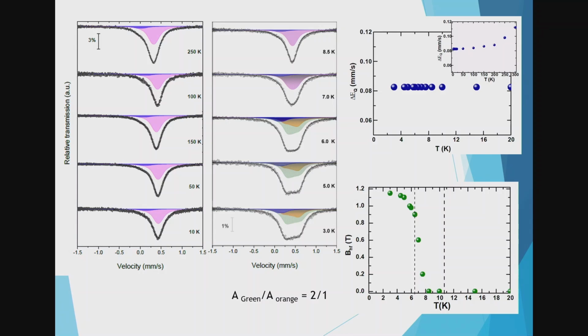And I assume these samples are polycrystalline samples. Polycrystalline samples, yes. Would it help to study single crystal samples? Yes, it would help a lot if I could find somebody to make it for me with iron 57. Yes, and I have a little bit of iron 57. This is a very nice sample to grow because of congruent melting, and it's very easy growing material, no problem.